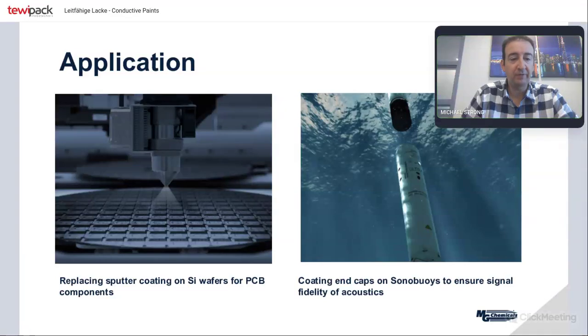Replacing sputter coating for silicon wafers. Silicone wafers are sort of the birthplace of the components on a printed circuit board. And so classically they would sputter coat these to make them electrically conductive, and that could be with gold or carbon. That is an expensive and very laborious process. It's also quite slow. You can replace that by putting thin layers of conductive coating, so long as the coating can be applied thin, is very conductive, but is also very flexible so that it doesn't shear and that you have good conformity to the part itself.